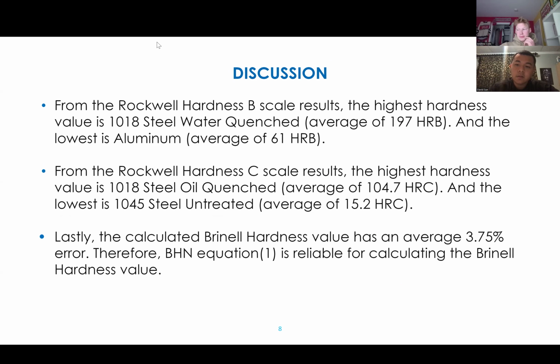For the Rockwell hardness B scale, the highest hardness was 1018 water quench, average of 197 HRB, and the lowest is aluminum, average of 61 HRB. And for the C scale for Rockwell hardness result, the highest was 1018 steel oil quench, with an average of 104.7 HRC, and the lowest is 1045 steel untreated with the average of 15.2 HRC. And for the Brinell hardness value, we yield a percent error of 3.75. Therefore the BHN equation is reliable to calculate the Brinell hardness value.